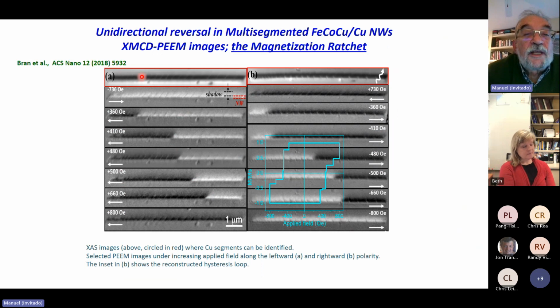I would also like to mention that we have done this type of experiments in these multi-segmented nanowires, and we have found what we have called the magnetization ratchet. You see, to the left, we start with a single domain structure, white contrast, under a negative field of minus 700 Oersted. As we remove the field and apply a positive field of increasing amplitude, we see that the magnetization reverses in different steps, reaching a negative contrast. Interestingly, the reversal starts at the end where we have the shorter segments of iron-cobalt.